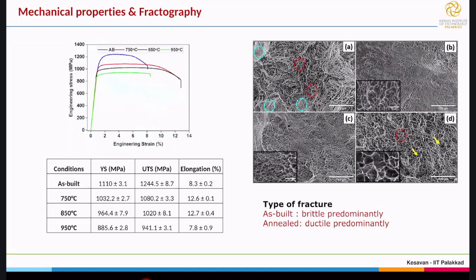So now this material, the as-built, as-printed material, is seen with very high strength. But the drawback is the ductility is very low. You see this blue curve, ductility is very low, so that actually puts us in concern. With the heat treatment, you can see that the strength has decreased, and the ductility is regained, right?